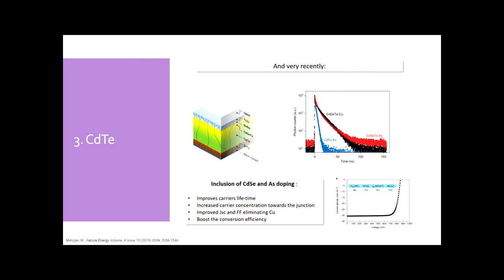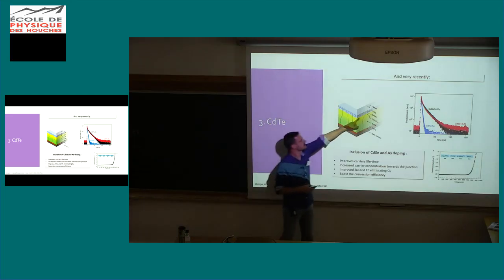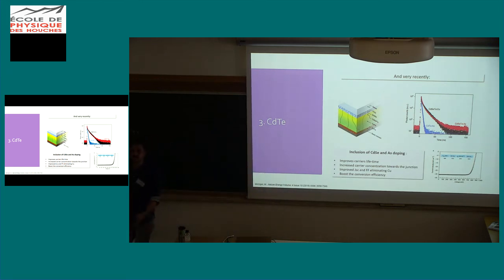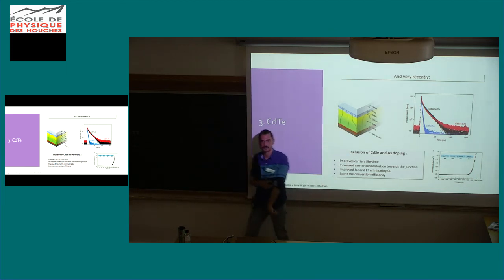The ternary compounds? Here, you mean? Here you create a graded band gap, like in CIGS. So you increase the band gap here, normally, then you reduce the hole concentration and you reduce recombination there, a lot of recombination. And also your surface has a higher band gap and it's to quite a large extent determining your VOC. Then it's like if you are using a wider band gap material with higher VOC. So you are increasing your VOC without sacrificing the current because the material is still 1.5 here in the bulk and you are absorbing all the light very efficiently. So it's exactly the same in CIGS.